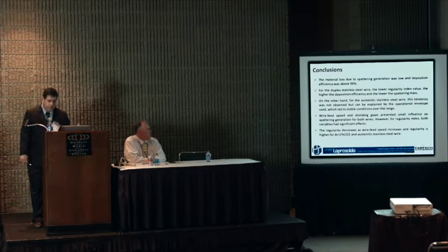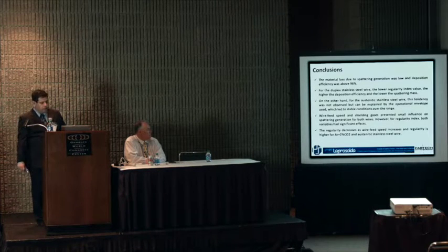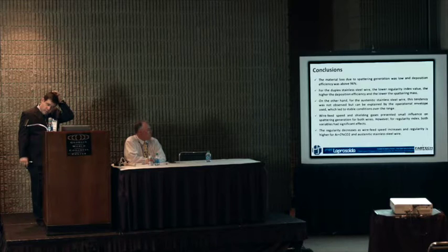On the other hand, for austenitic stainless steel, we cannot. Perhaps, I don't know, we still have to look into the metallurgy, which is definitely important, because this index works really well for carbon steel, which means there's a lot of ferritic. So maybe the 50% of ferritic part in the duplex could make it work like a carbon steel, we don't know. We still have to look into the metallurgy.